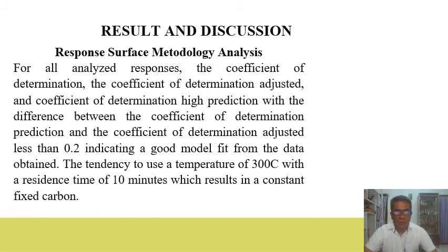Response surface methodology analysis. To analyze the responses, the adjusted coefficient of determination and the predicted coefficient of determination are used, with the difference between the predicted and adjusted coefficients of determination less than 0.2, indicating a good model fit to the data obtained. The tendency is to use a temperature of 300 Celsius with a residence time of 10 minutes, which results in a constant fixed carbon.